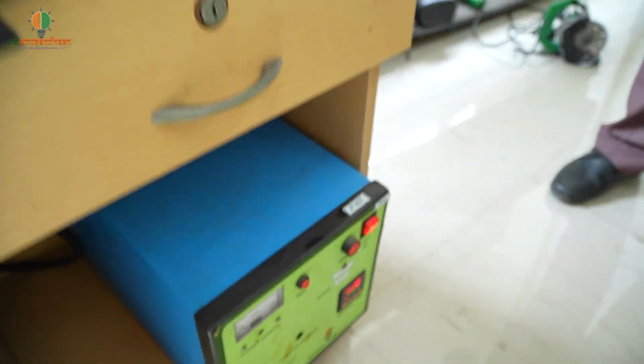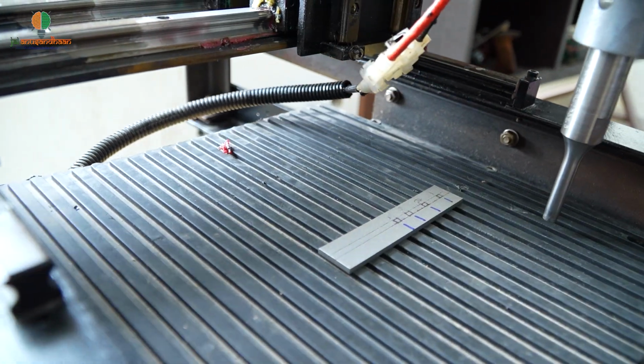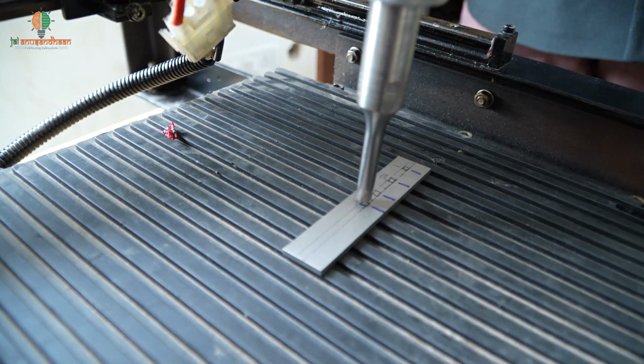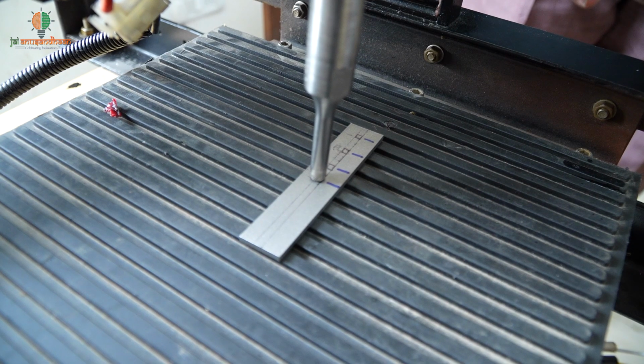The technology we are using imparts an ultrasonic vibration over the material. We have made the sonotrode, or the probe, vibrate on the material which is induced with residual stresses at a very high frequency, about 30,000 hertz or 30 kilohertz, and at very low amplitude. The amplitude would range between 30 to 40 microns. The frequency and the amplitude can be varied depending upon our requirement.